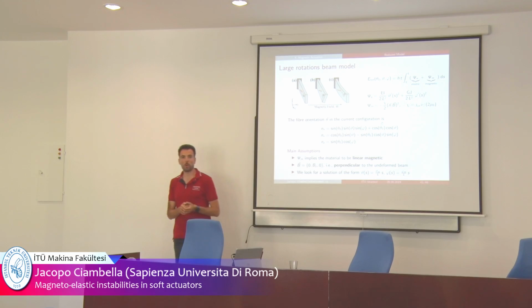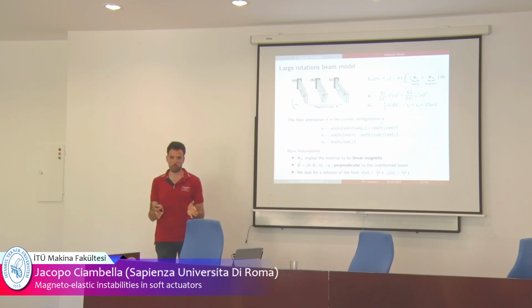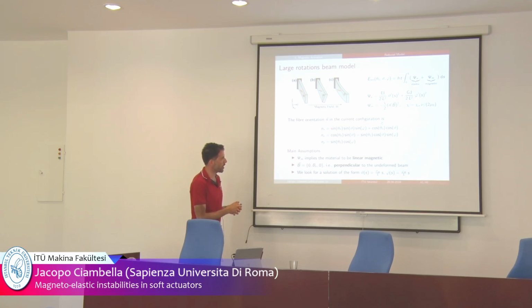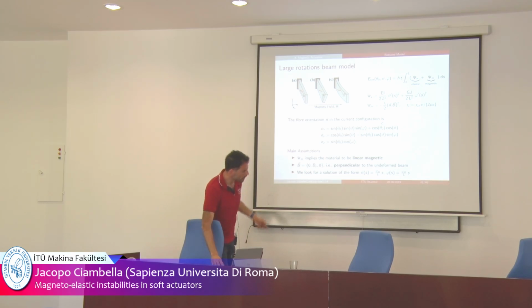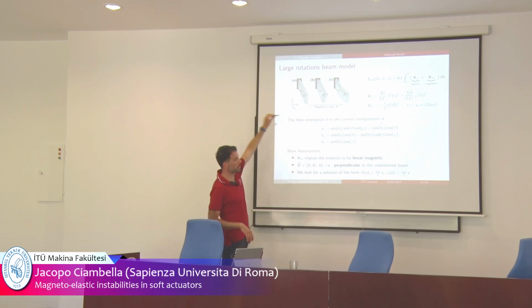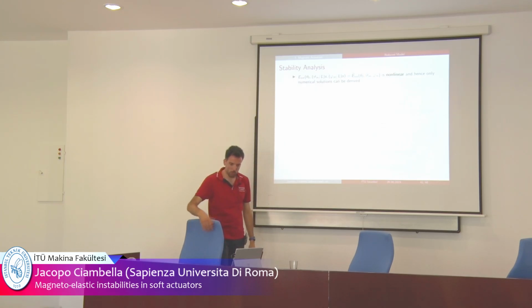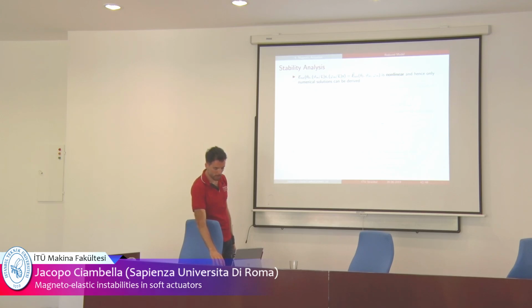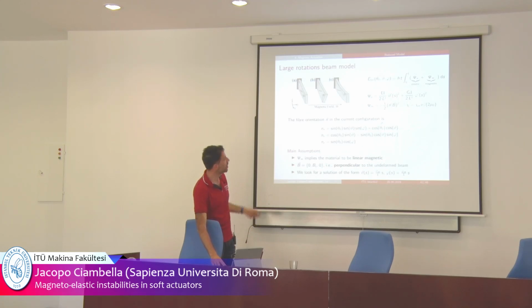You can work out the Euler-Lagrange equation for this problem, so the governing equation of this problem, in terms of the angles theta and phi. Theta, I say again, is the bending angle, and phi is the twisting angle of the specimen. In our experiment, B was directed along y. Okay? It was in this direction here. And so you can do stability analysis, for instance, because the total energy is nonlinear, okay? Because of this sine here. In this equation you have cosine squared, so the governing equation is nonlinear.